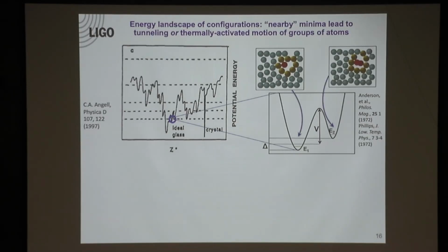Now, what's called the tunneling level states, which I'm not going to show you, I'll just flash through a couple of slides. The explanation of those low temperature glass properties lies in states that you can either thermally activate over or you can tunnel between. A theory was developed for these tunneling level states where, once you mix, each individual state becomes a pair: psi1 plus psi2 and psi1 minus psi2. The energies are now mixed, and the splitting of those states is micro-eV. Everything else in this energy diagram is sort of eV, or maybe milli-electron volts, but it's definitely not micro-electron volts. So the only way you can get to micro-electron volts for energy splittings is through this tunneling idea. I show you schematically, it's not tunneling of a single atom, it's tunneling of a whole group of atoms together.